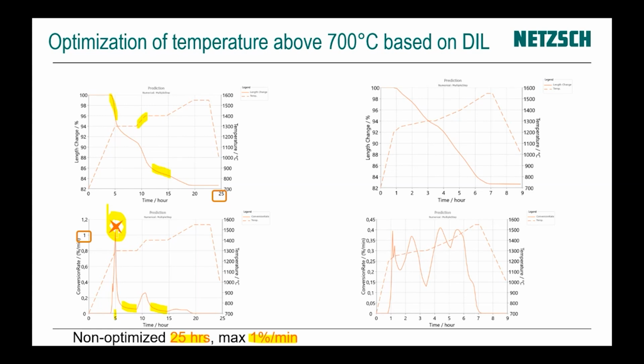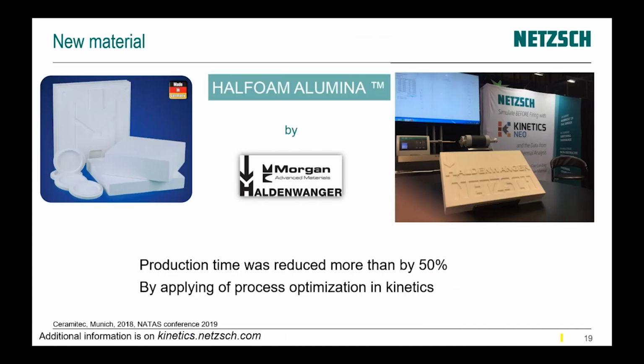After our optimization inside our software, we have finally a result of 9 hours. It's more than twice less, and the maximum shrinkage rate is 0.4% per minute. So it's more than twice less. In this case, we have improved the quality and we reduced the total time and we reduced the costs of our material, of our production. That was one of our first customers where we applied this optimization, and that was the company Haldenwanger.